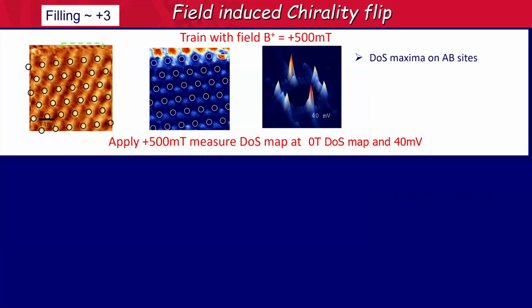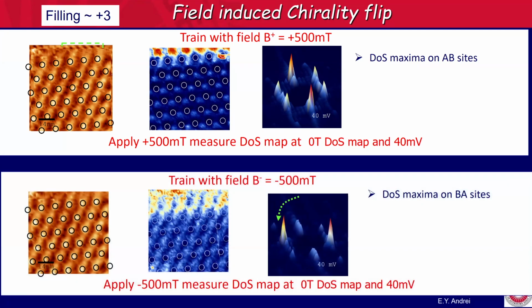And when you take a Fourier transform of this, you see that you have enhancement of scattering perpendicular to the boundary, and it's kind of suppressed away from it. And next we go to the other side of the magnetic field. We apply a negative magnetic field. We train it with minus 500 millitesla. And now the wave function has shifted in another direction, closer to the BA side. And the Fourier peak here has kind of turned by 60 degrees.